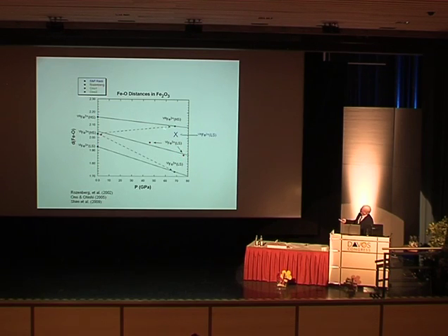The Ono et al. work presented these results, in which it appears that iron 3+ probably went through the Rh2O3 structure and then to the post-perovskite structure with iron 3+ in 8 coordination. And the other site would be iron 3+ in 6 coordination, low spin.